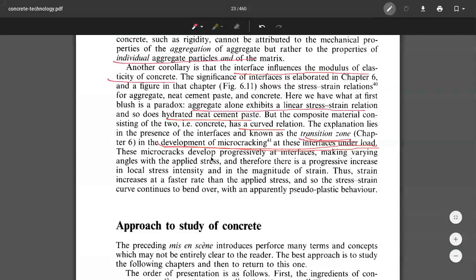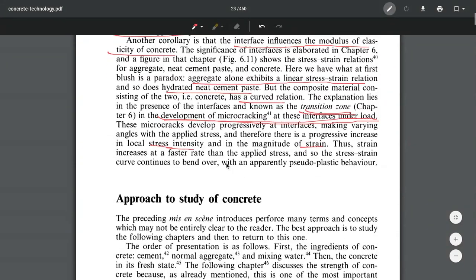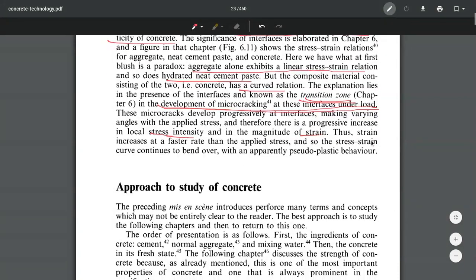So these microcracks develop progressively at interfaces, making varying angles with the applied stress, and therefore there is a progressive increase in local stress intensity and in the magnitude of strain. Thus, strain increases at a faster rate than the applied stress, and so the stress-strain curve continues to bend over with an apparently pseudoplastic behavior. As stress increases, strain increases at a faster rate than the applied stress. So the stress-strain relation becomes pseudoplastic, and the graph is curved in nature.